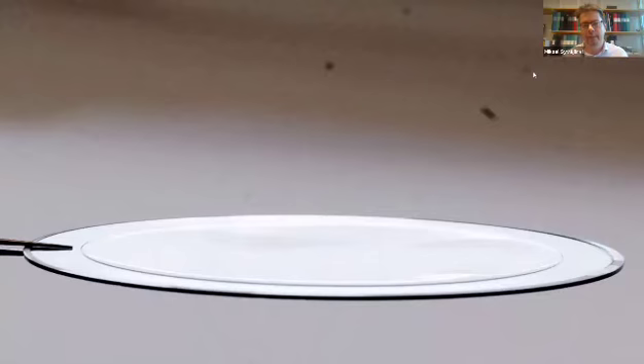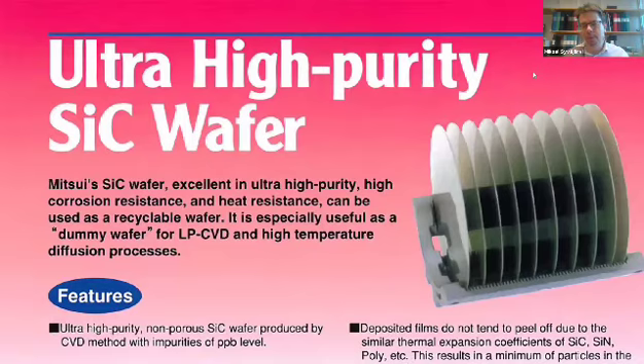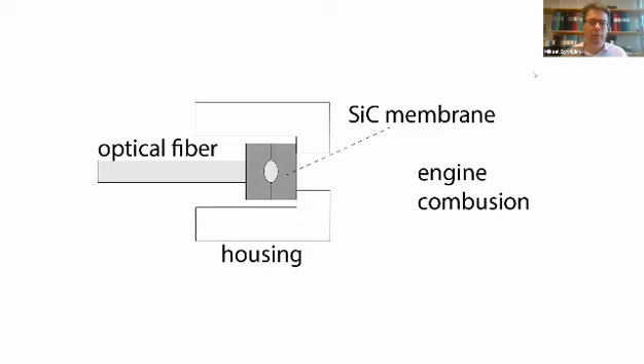And if we go back to this sublimation epitaxy method, where you had thick layers grown on wafers, substrates, and we were using the ceramic silicon carbide as a source. But then we came into another avenue, because one day, maybe 2 years ago or 2.5, 3, one guy called me and said that I would like to have a silicon carbide cavity where you have 2 wafers of silicon carbide and we bond them to each other in a close way. And in the center here, you have a cavity.